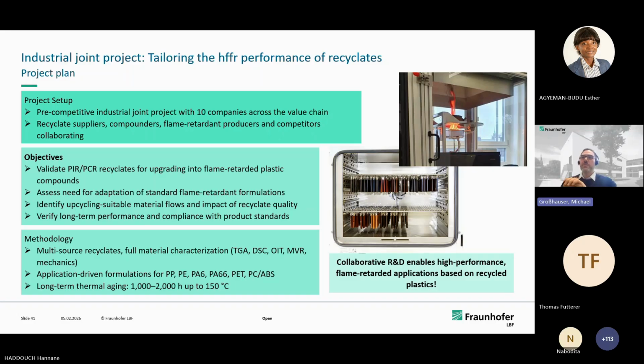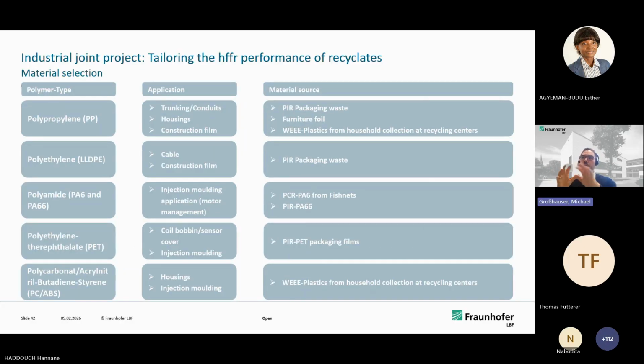So we used multi-source recyclates and did a characterization with the methods you see, and we have application-driven formulations we did together with the participating companies for the materials you see down there, and also thermal aging from 1,000 to 2,000 hours up to 150 degrees. And this collaborative R&D method enabled that high-performance flame retardant applications are basically doable based on recyclate plastics. Next slide, please. Just to give you an overview, the material types we looked into inside of this project, the applications that could be done with those materials, and the sources we evaluated for this project.